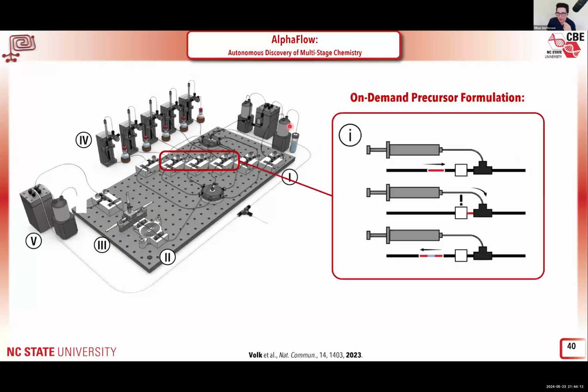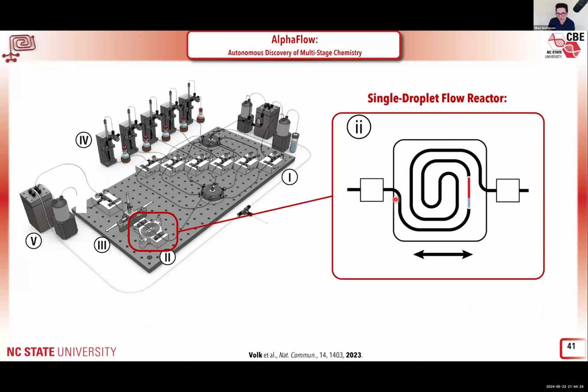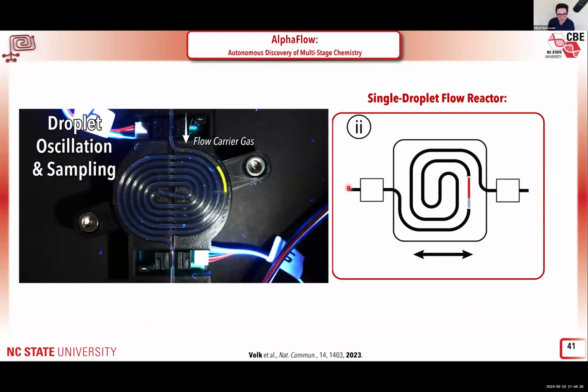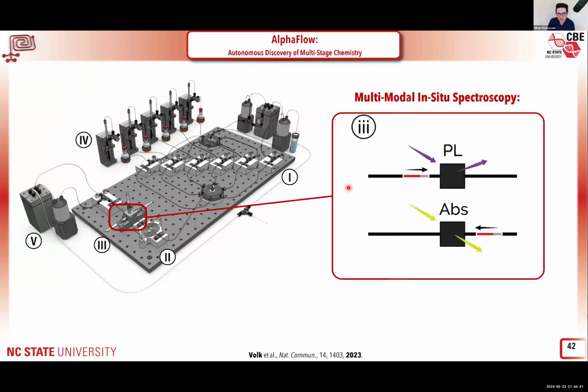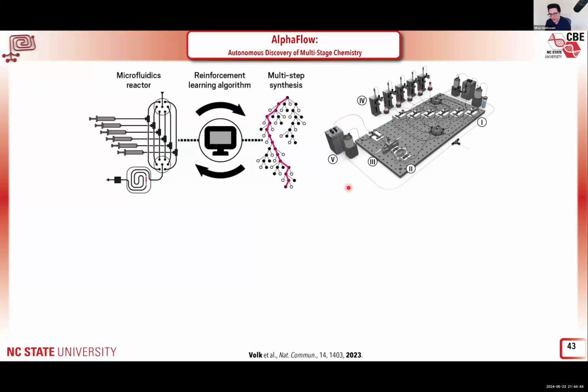So here we have our on-demand precursor formulation, and we can bring a droplet into a T-junction, and the setup can automatically inject into the droplet whatever volume of whatever precursor that it wants to inject. Here's where we do the synthesis of each half cycle. So here is a video of this single droplet moving in our flow reactor, and we use pressurized inert gas to control the movement of this droplet in our flow reactor. And then we do in situ spectroscopy, and at the end we have purification. So we call this autonomous lab Alpha Flow because the dimension here is, as I said, 40 different parameters. And instead of using Bayesian optimization, in this case, we use reinforcement learning to navigate this high dimensional experimental space.